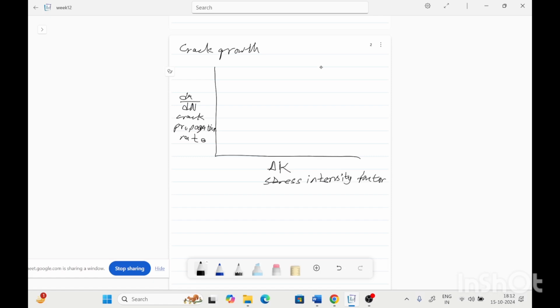So in this curve we get a sigmoidal type of curve. The first region decides the threshold stress intensity factor, below which no crack will propagate. So this is stage 1, this is stage 2, and this is stage 3. The delta K value at stage 3, when the sample fractures, can be represented as the fracture toughness of the material or composite.